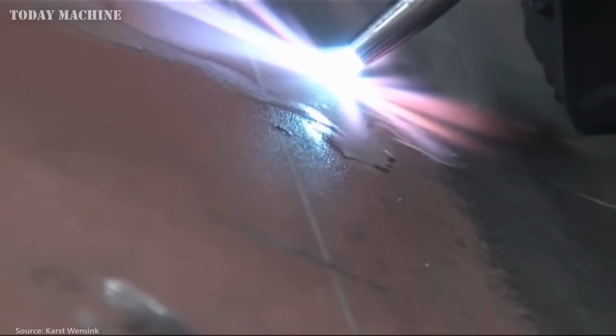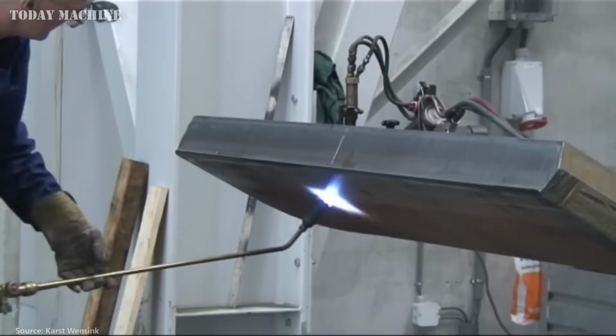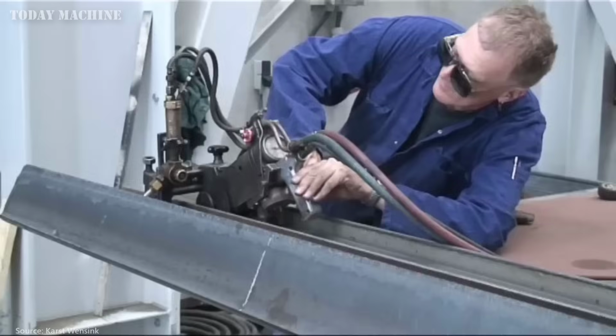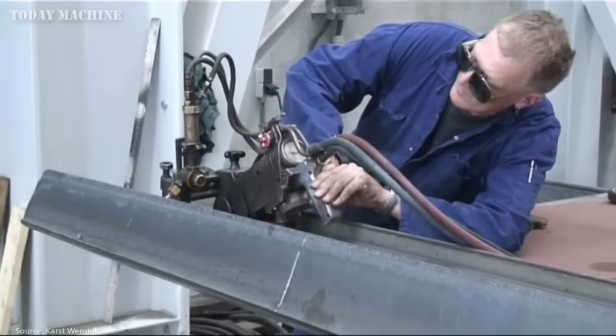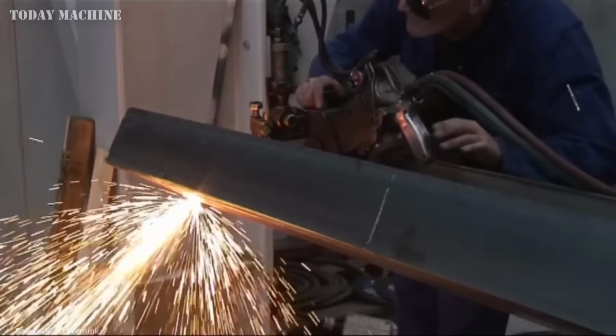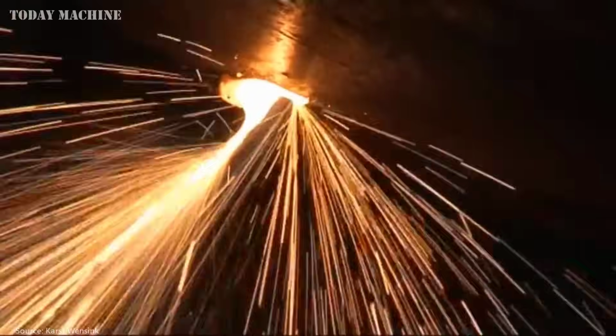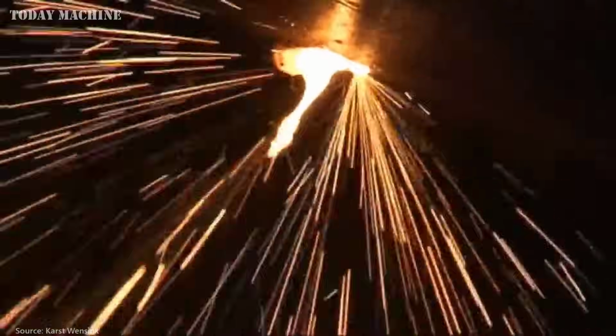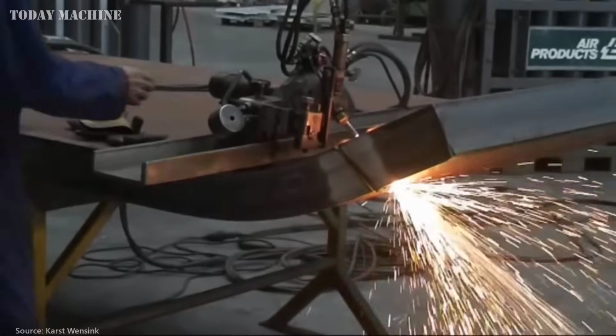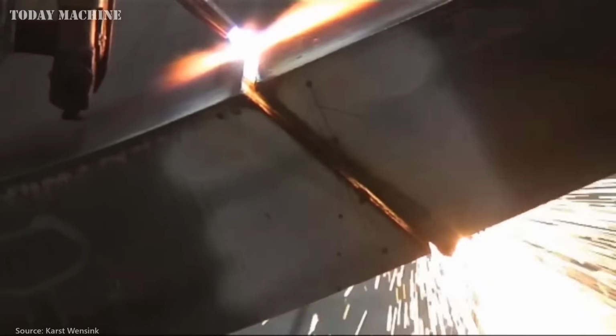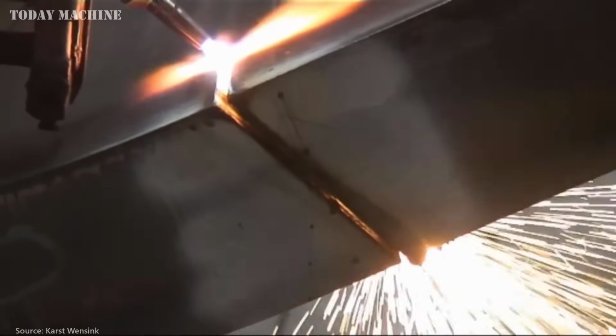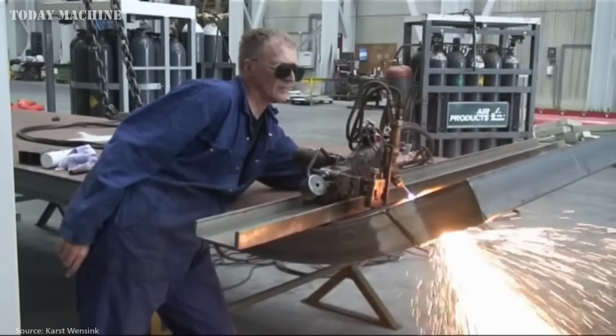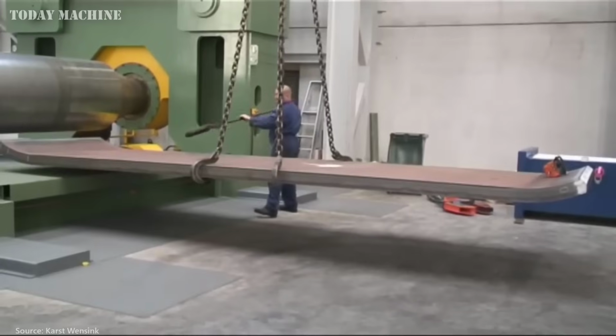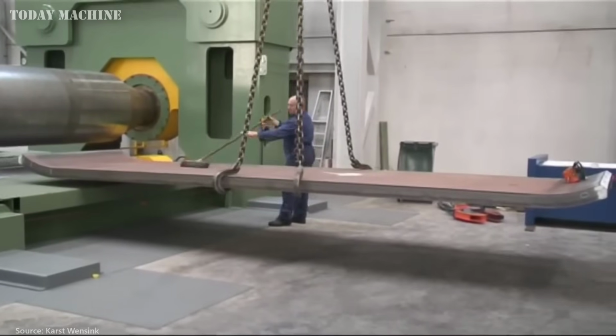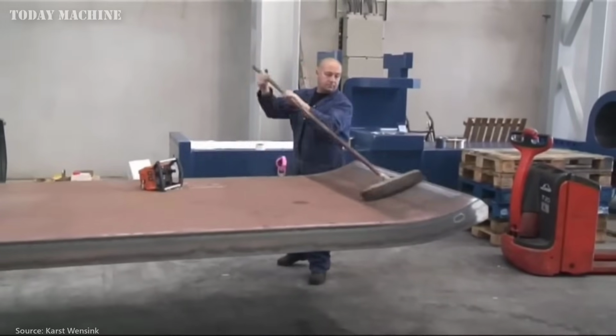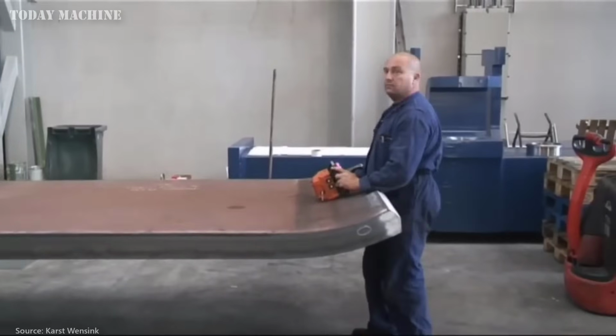The rolled shell from this machine achieves an external diameter of 2076 millimeters. The welding of the seams is performed using a highly productive method that ensures rapid and efficient filling of the joints. In some cases, welding is done with two filler wires simultaneously, further accelerating the process. The welding wires are coated with a protective powder layer, and any excess powder is recycled for reuse.